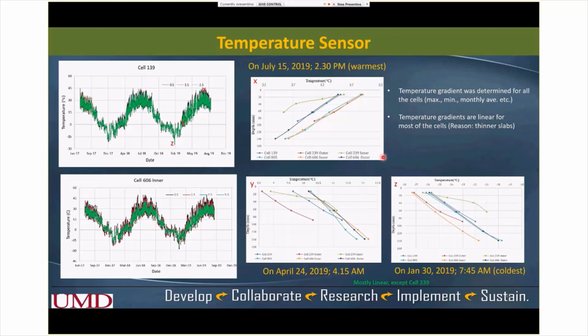We collected temperature data at different depths of the pavement, and we are collecting the data throughout the season. These two graphs on the left show how temperature varies with respect to the season, and then we calculated the temperature gradient. Just as an example, X, Y, and Z are three times, at high temperature, low temperature, and an intermediate temperature. In all three times, we found that the thickness of the slabs here is 3 to 5 or 6 inch, right?